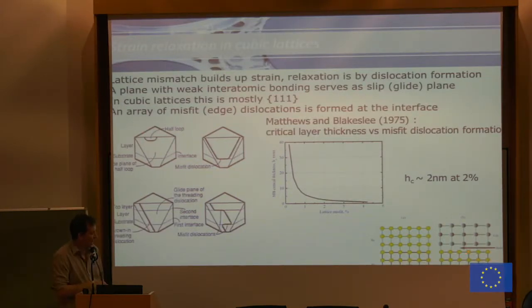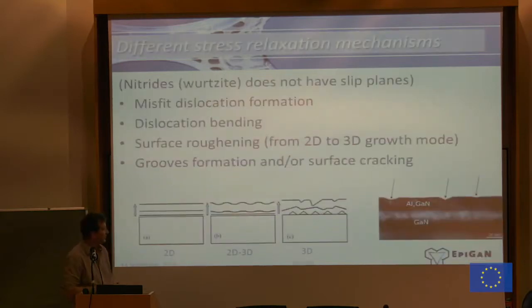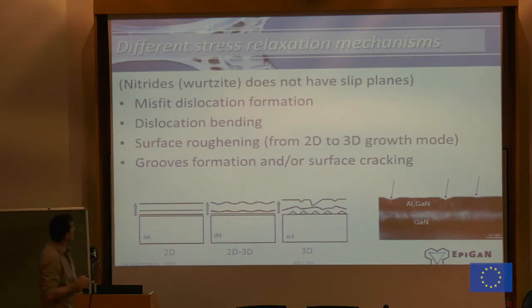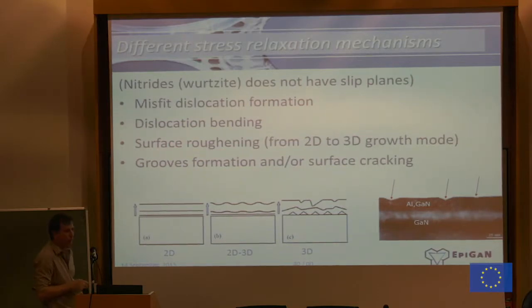And the end result is that you have a threading dislocation and an edge dislocation at the interface between the two materials. So it's really a dangling bond in the crystal there. As I said, it is from cubic materials, so it is not the case for gallium nitride. And in gallium nitride, you have a whole different set of mechanisms. I think also here Elke will probably say more about that. Important ones that I will come back to later are the bending of dislocations because of the strain, the surface roughening, so moving from 2-dimensional growth to 3-dimensional growth, and the formation of grooves in the surface. And also there I would like to say a few more words in a few minutes.